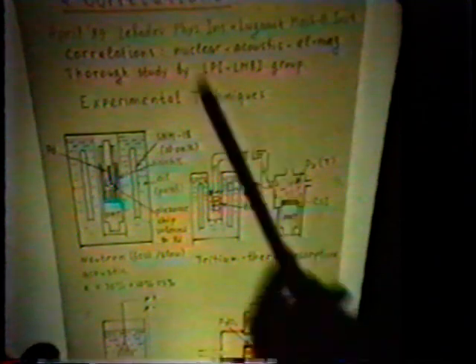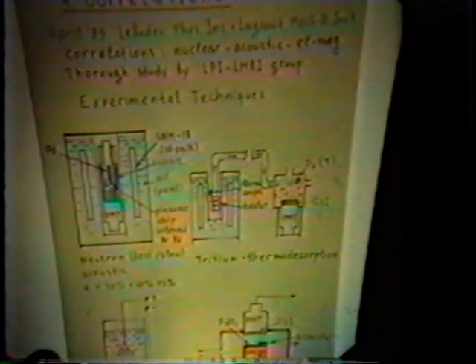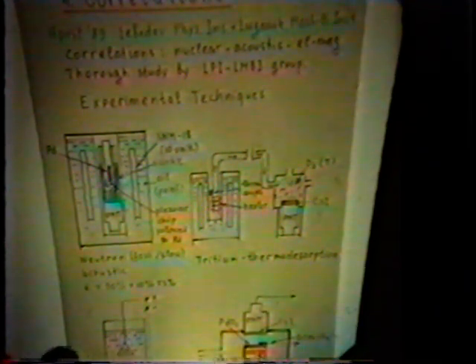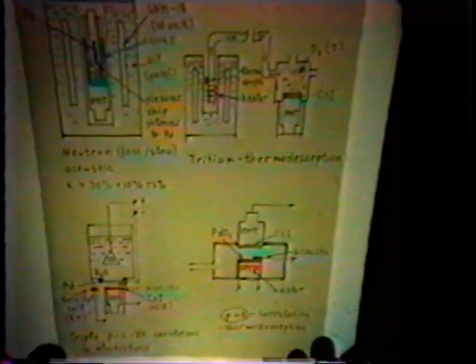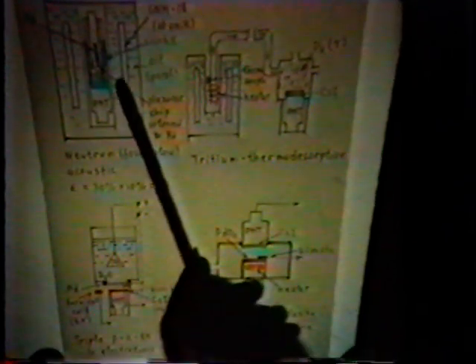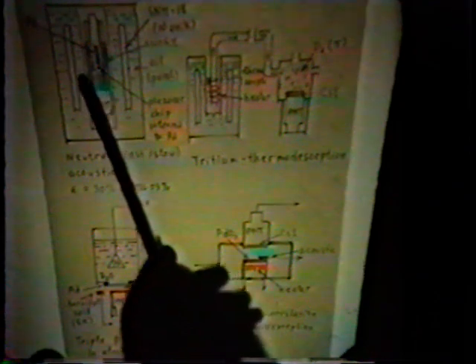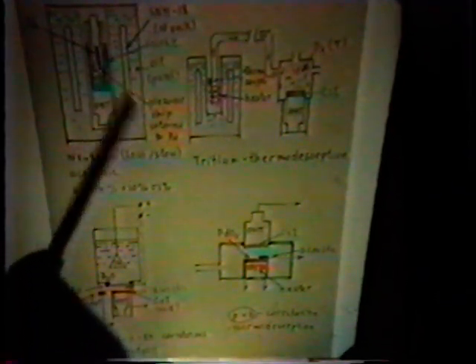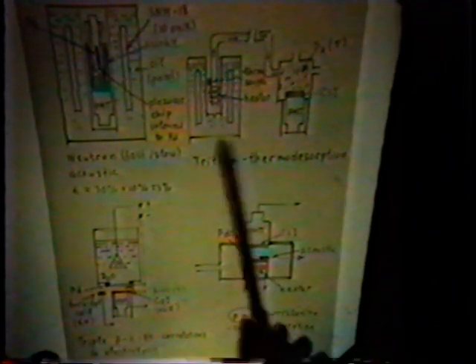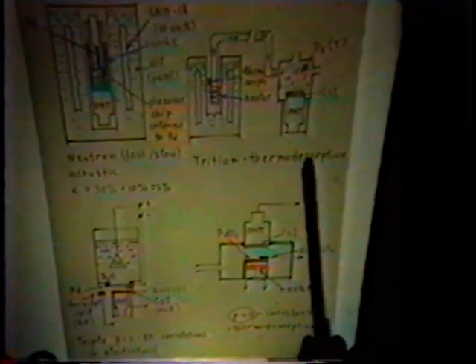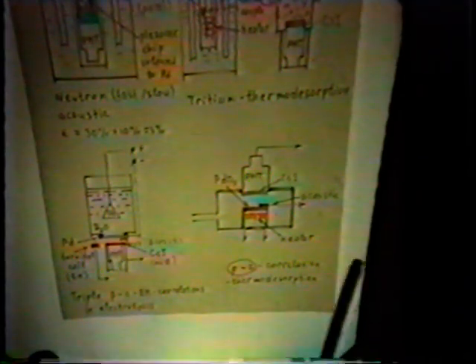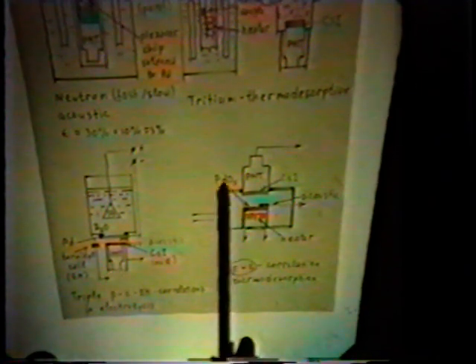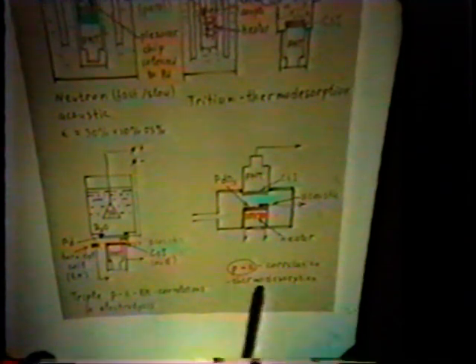The next topic is correlations. In their early work, the group from the Lebedev Physical Institute at Lugansk suggested measuring correlations between nuclear products, acoustic and electromagnetic signals. Starting from about the middle of 1989, this group performed a thorough study of this phenomenon. Here you can see some examples of the apparatus used by this group. Here you can see the neutron counter with counters for slow neutrons and fast neutrons, and sometimes they also use a piezoceramic chip soldered into the palladium cathode to measure the acoustic signal. Here is the setup used for tritium search during thermal desorption, this setup was used for searching for triple correlations during electrolysis, and this setup was used for double correlation search during thermal desorption.